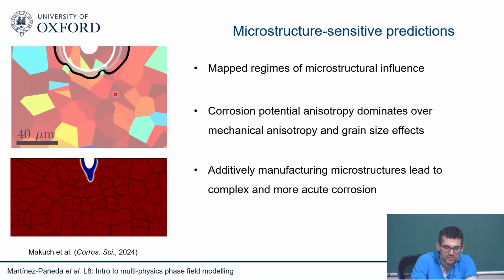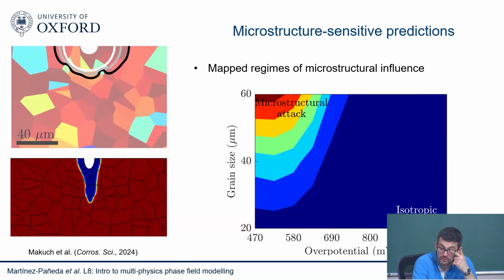And you need to run multiple calculations just to account for some sort of statistical scatter. And what we learned, the things that we were interested in, is first, we wanted to map the regimes of microstructural influence. So when do we need a model as complicated as this one? And when can we get away with an isotropic model? And this is what we did. So it depends on many things. Among others, the size of your pit. If your pit is much larger than your grain size, or versus the grain size, or the overpotential, the conditions where you have more activation versus diffusion control corrosion. But this was the idea.